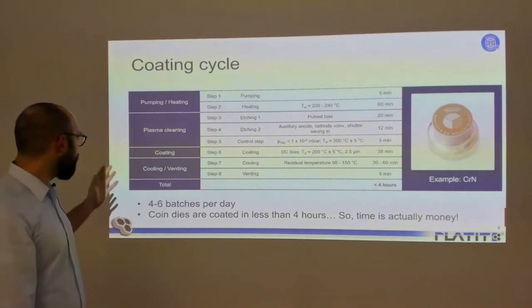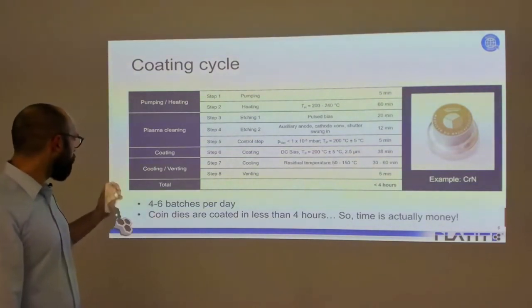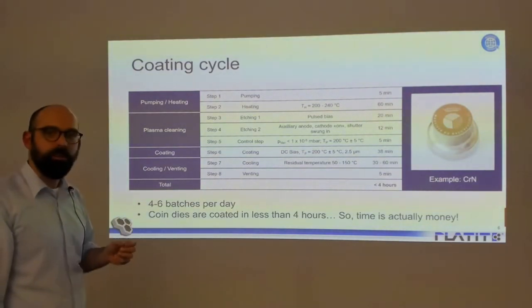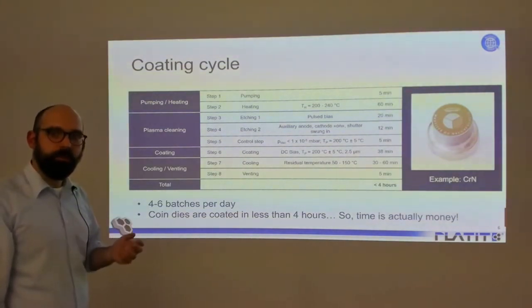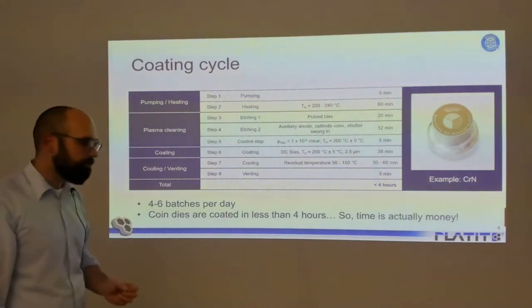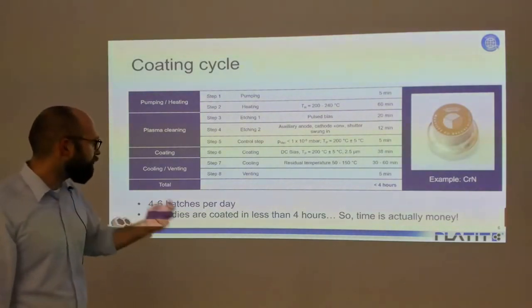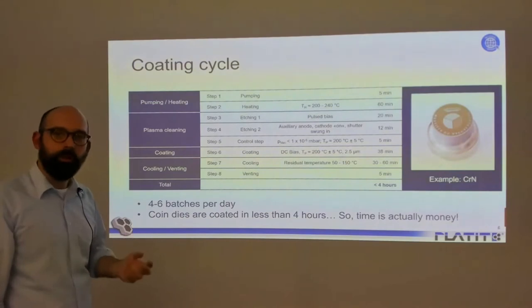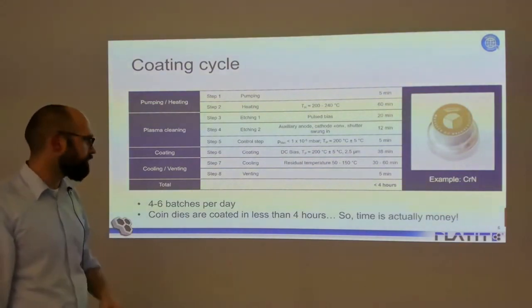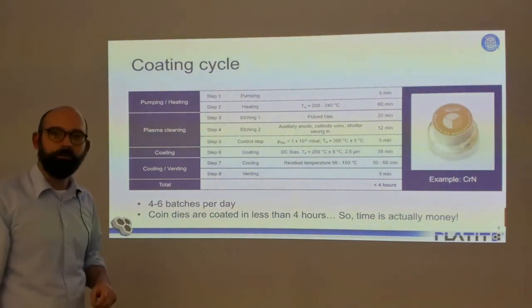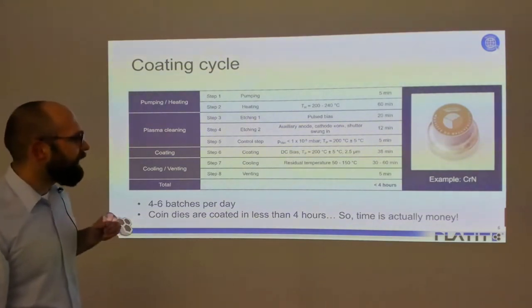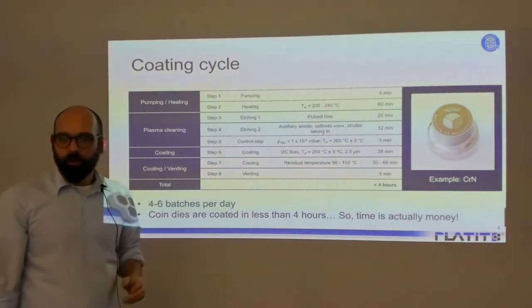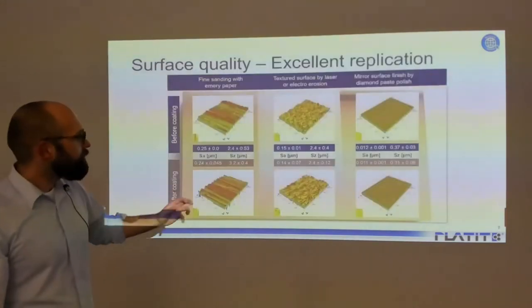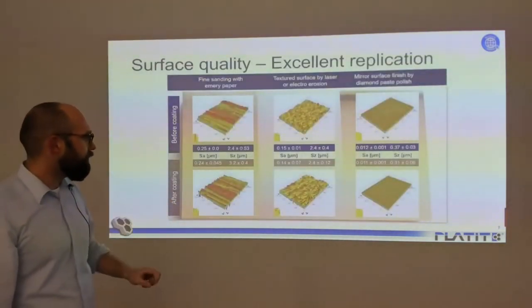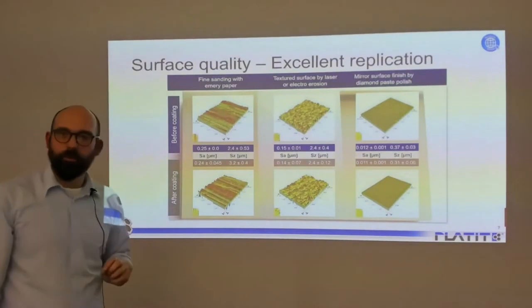This means that within one day, you can coat up to 4 to 6 batches. This is really good productivity considering that you can load up to 18 punches in one single batch. Or in other words, after 4 hours, you have your perfectly coated stamp in hand ready for production. Time is actually money here. And since I cannot stress the surface quality enough, let me show an example of how good the surface qualities of coatings from the S-impulse are.